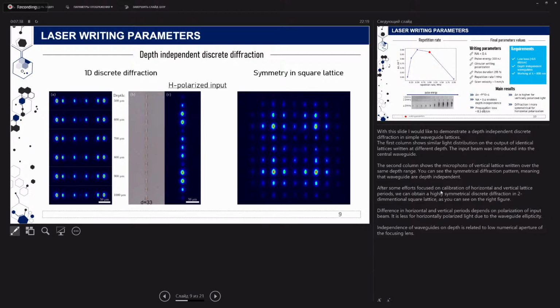After some efforts focused on calibration of horizontal and vertical lattice periods, we can obtain a highly symmetrical and discrete diffraction in a two-dimensional square lattice, as you can see on the right figure. The difference in horizontal and vertical periods depends on polarization of the input beam. It is less for horizontally polarized light due to the waveguide ellipticity. Independence of waveguides on depth is related to the low numerical aperture of the focusing lens.